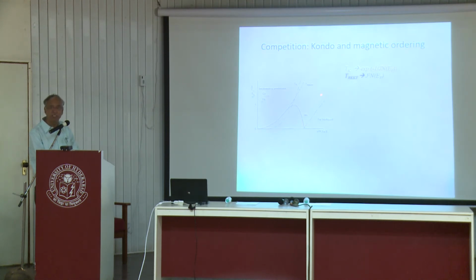Okay. Today, there are many explanations. I will not go into the detail. The current people are trying to argue for various reasonings. They are trying to explain what is the origin of what is called non-Fermi liquid behavior. And most interestingly, at the same point, you do find superconductivity coming into the picture, where you have non-Fermi liquid behavior here. By the way, this is a degree of delocalization. When I say the interaction parameter increases, you are increasing the degree of covalent mixing, the degree of hybridization. You are increasing the hybridization of the 4f shell, or increasing the tendency for delocalization. You are ending with a very complex behavior at some point in the magnetic phase diagram.